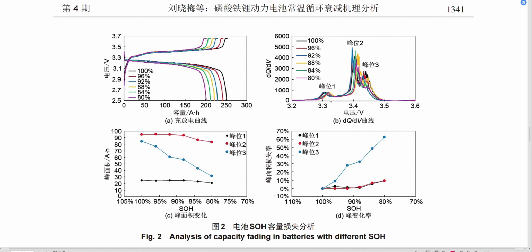The black dash dot, which is peak 1, is generally not changing too much. Peak number 2, which is at 3.4 volt in red dash dots, slightly drops during 90% to 80%, and peak number 3 in blue dash dots, which is at 3.45 volt, is a major decreasing peak. So you will see the major peak area loss is peak number 3.